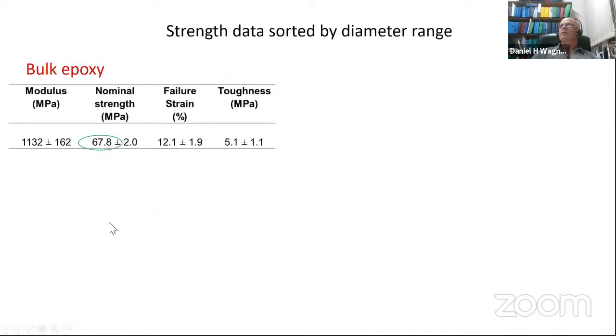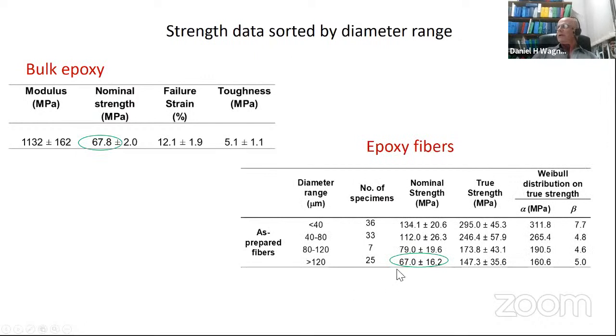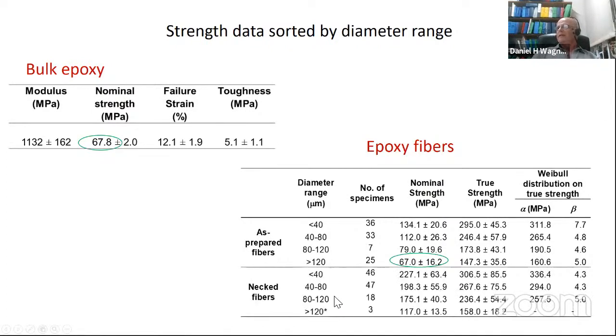And let me show you this in a table. This is the value for bulk, and also for fibers that have a diameter above 120 micron. The value for the fibers then increases from 67 to 79 in the diameter range down to 80 micron, and then down to 40 micron you reach 112 megapascal strength, and then below 40 micron you have 134 megapascal, which is, I mean, it's amazing. There are other data here, but it's not necessary to talk about this right now.